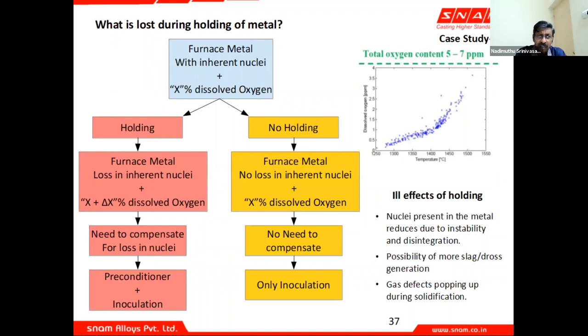Now, what exactly is lost during prolonged holding? The furnace metal has inherent nuclei, and it has some percentage of dissolved oxygen. When you keep holding the metal, the natural tendency is to raise the temperature and hold the metal. As you raise the temperature and hold the metal, the other oxides and sulfides that are there disintegrate, and the dissolved oxygen percentage keeps on increasing.